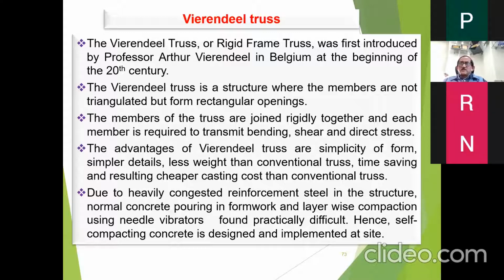Due to heavy congested reinforcement steel in the structure, normal concrete pouring in formwork and layer-wise compaction using a needle vibrator was found practically difficult, and self-compacting concrete was designed and implemented. Why we went in for it is because of two problems which we foresaw. That is because of the heavy congestion, which I used to say would require self-compacting. And when the site people saw that the beams are 1.5 meter depth, it would be very difficult to compact the concrete when you put it down, because there are slender sections and deeper sections, so it would be difficult. So then we shifted to this type of concreting.